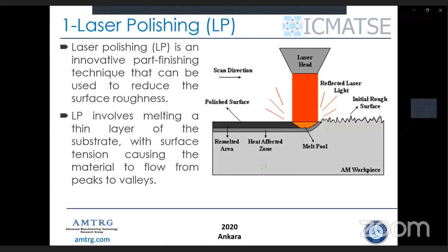As you see in the figures, laser head moves from one side to other. With the movement of the laser head, a thin layer of the surface melts, and then, with the effect of the surface tension and the gravity, melted materials move into the pits. In this way, more smooth surfaces could be achieved.